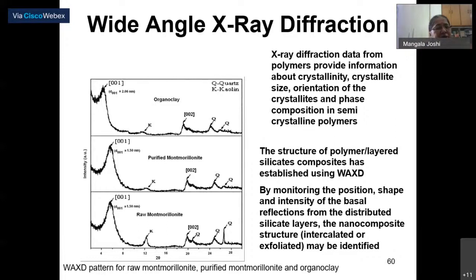If your peak is a sharp peak, but it comes as a very low or a shifted peak, then you can see it has intercalated, that means the distance between the clay platelets has increased. If the peak is totally distorted, then that means the clay has totally exfoliated into the sample. XRD is a very, very important tool for us who do research in polymer, clay, or any kind of nanocomposites to look at the distribution or dispersion of the nanomaterials in the polymer.